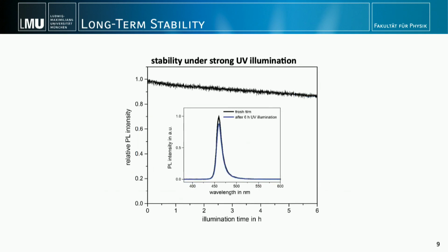And I also want to show you how they behaved under strong UV light emission. Even after several hours of strong illumination, the efficiency stayed between 80 and 90%, which was quite good, because other platelets or previous samples were destroyed within a few minutes.